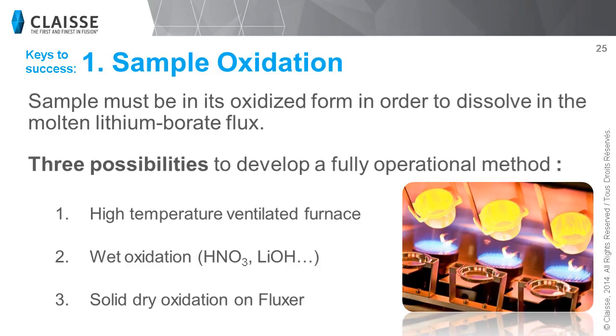The key to perform the solid dry oxidation on a fusion instrument is to control the fusion temperature and agitation at the beginning of the fusion program. As a matter of fact, we have to first melt the oxidizer, which will oxidize the sample. This step is performed at a lower temperature than the temperature used for the fusion process. If the fusion temperature is too high, the oxidizer could volatilize or decompose before the end of the oxidation reaction.